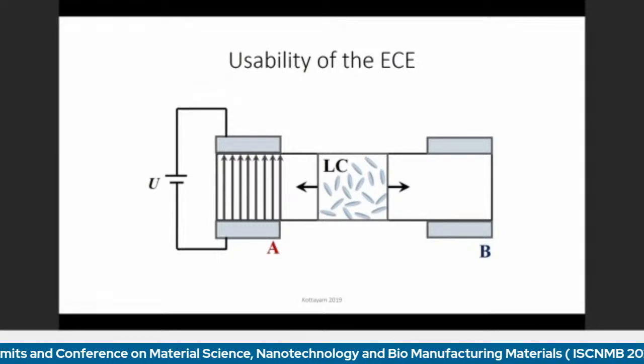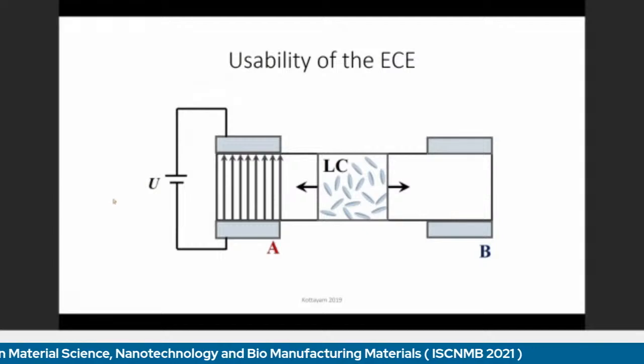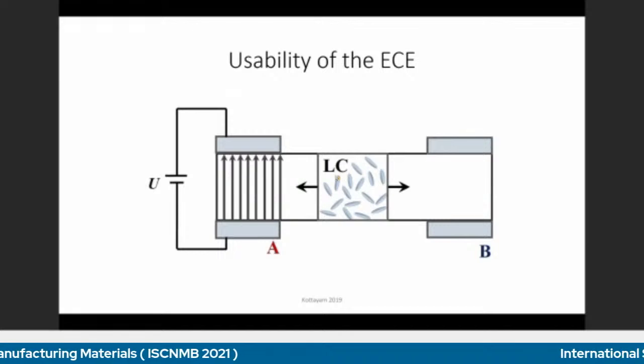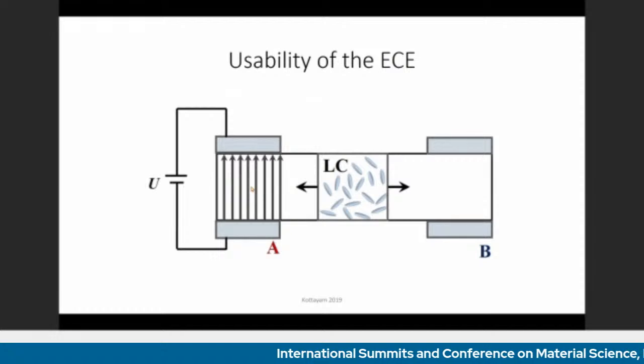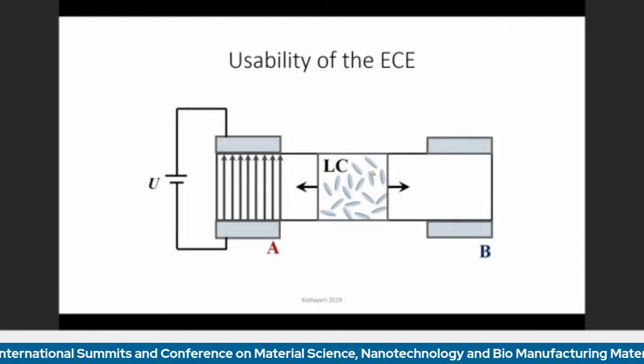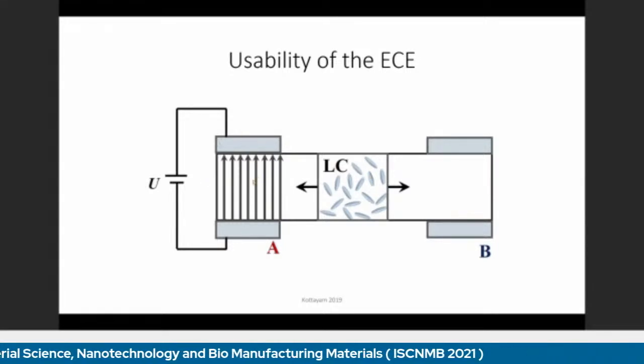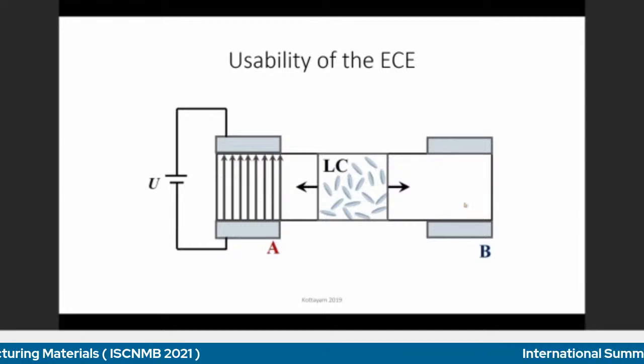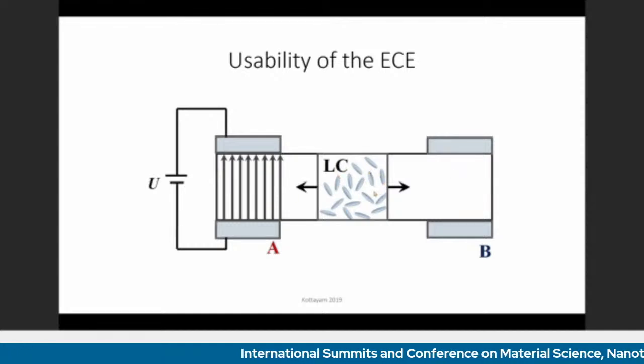If we continue to how to use this, we see that we can establish even larger temperature gradients if we move the liquid crystal between two parts of the system. Let's suppose that we can shift these liquid crystals into position A or into position B. If we move them to position A, there is an electrical field and the liquid crystal gets aligned. If we shift it to position B, there is no electrical field and the liquid crystal goes to the isotropic phase, so they are in disorder.